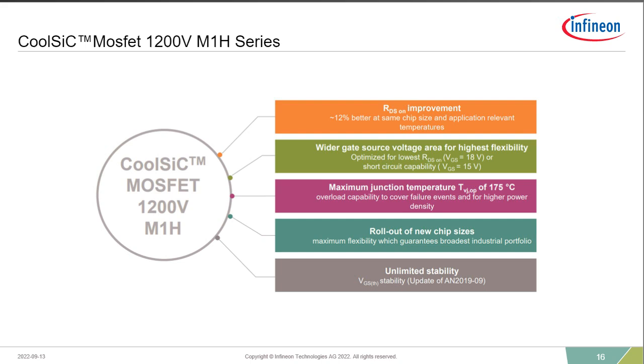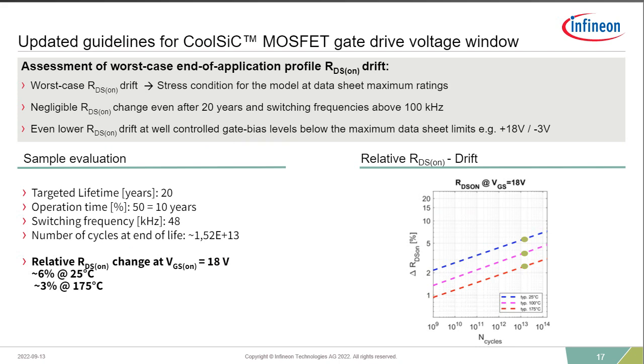And then the biggest advantage here is we've improved the long-term stability of silicon carbide. So silicon carbide has historically always had a condition where the more negative you drive the gate, so let's say -5 or -10 volts, the higher the shift in RDS(on) specification that you would have in the device over its lifetime. And we've been able to prove now with the M1H technology that we can guarantee a less than 3% shift in RDS(on) specification at 175 degrees C over a 20-year lifetime of the product. So the Infineon devices are very stable.